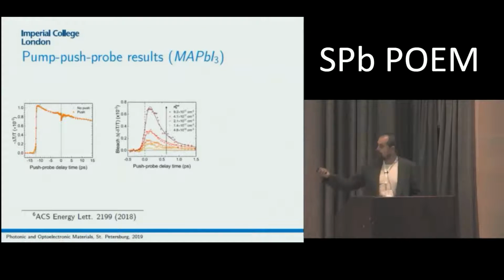If we plot the difference between these two graphs to reveal just the push dynamics at different push intensities, which correspond to different concentrations of hot carriers, we can reveal the dynamics and fit it with exponential processes.